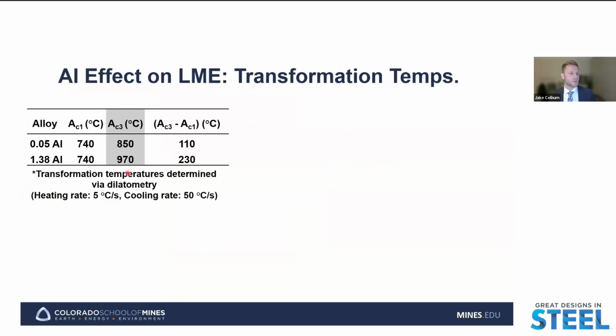to somewhat make sense as we compare the AC1 and AC3 temperatures for these two alloys, where the AC1 temperature, so that being the temperature upon heating at which we enter the austenite plus ferrite two-phase region, we see roughly equal values there, 740 degrees C for the two alloys. But then as we look at the AC3 temperature, so that's the temperature heating from the austenite plus ferrite two-phase region into the single-phase austenite region, we see an increase of roughly 120 degrees Celsius for the high aluminum alloy,